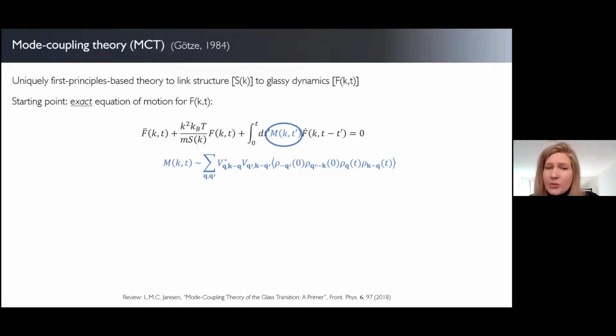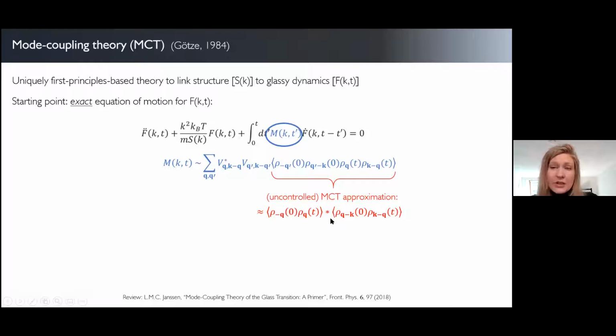Now, the problem is that we don't know what this 4-point density correlation function is because we don't even know what the 2-point density correlation function is, for which we wanted to solve this equation in the first place. So what to do? Then mode coupling theory does essentially the simplest non-trivial thing you can do, which is to factorize these 4-point density correlation functions into a product of two 2-point correlation functions. Now, there's not necessarily physically any good reason to do this, so it's actually an uncontrolled approximation.